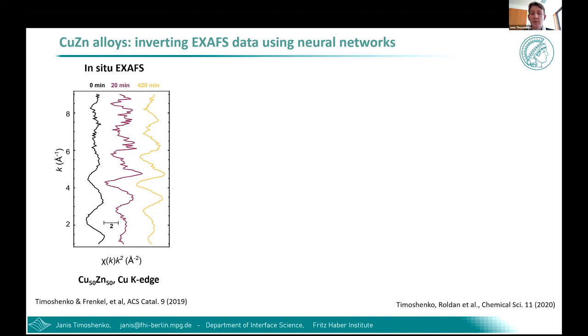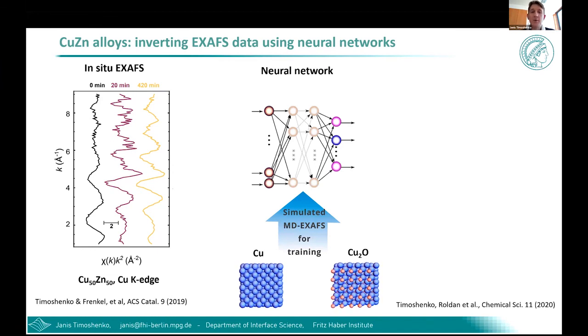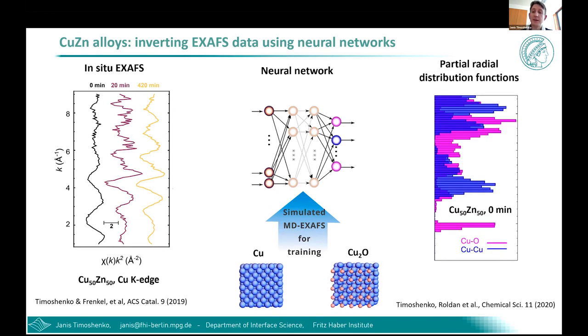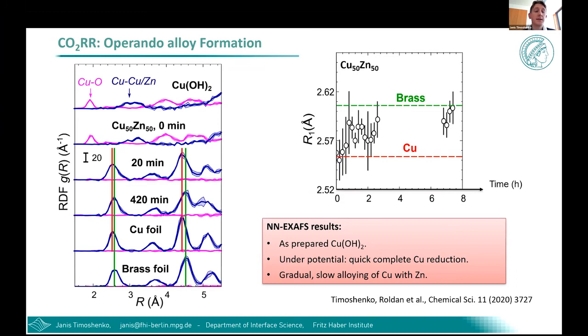To extract such accurate information, in this case we relied on a quite advanced data analysis approach based on machine learning and neural network analysis, which allows us to establish a direct relationship between spectral features in our EXAFS spectra and the entire bond length distribution function, or radial distribution function. The radial distribution functions for our copper-zinc nanoparticles are shown here. Here we see the radial distribution function for the as-prepared catalyst, and it's very similar to the local structure of copper hydroxide. We see a contribution of copper-oxygen bonds, but also some copper-metal contributions. When we apply the potential, the copper oxide contribution is gone, and we are left only with the metallic fraction.